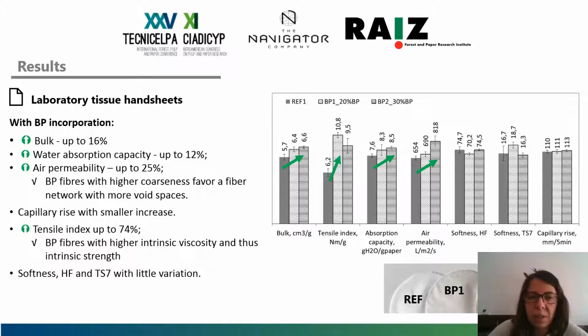As regards tensile strength, tensile index, it was found an increase, and this increase in strength was attributed to the fact that we are incorporating fibers with higher intrinsic viscosity and thus higher intrinsic strength. In case of softness, this parameter was analyzed for all formulations and no significant variations were found.